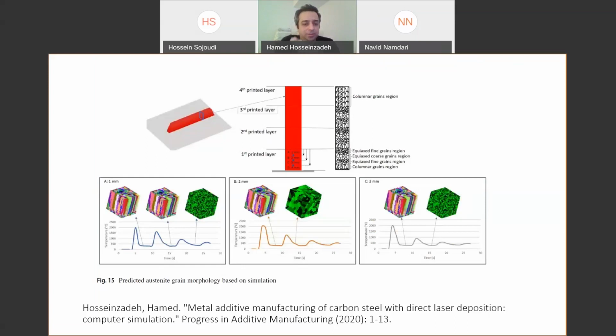It's a scale from green to black, and each color means a grain. You can see for point A, point B, and point C, at the end, we have different grain sizes. So if you repeat this for different critical points in the sample, we can prepare a map of the microstructure of our sample. If we have a complex structure, we can add some computational sensors at different sections and